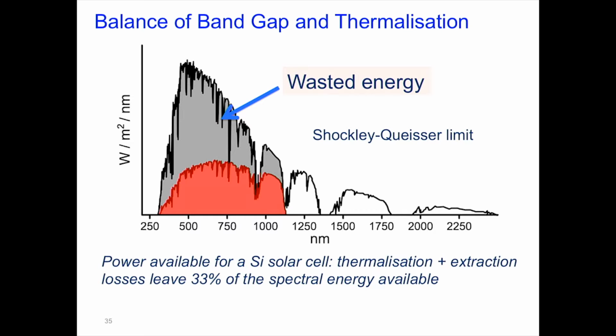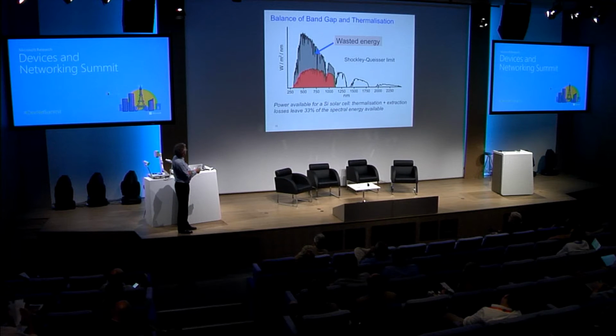And a lot of that wasted energy is that the lowest energy photon that's absorbed at 1.1 eV does just as good a job as a nice visible photon with an energy of 2.2 eV or higher. So by the time you get to 2.2 eV, there was enough energy to have created 2 electron-hole pairs, but in silicon we'll only get 1. So that limits the energy that you get from a single junction cell to about 33%. So the very best single junction cells based on gallium arsenide are up to, I think, 28.5%, but it's still not 100.